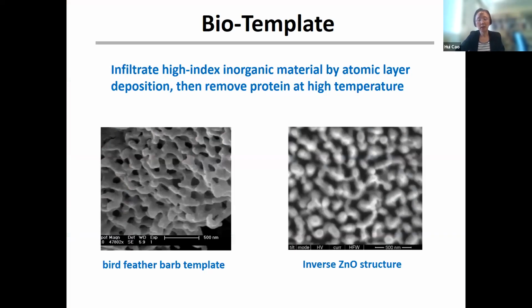But typically this phase separation worked very well, usually for soft matter, like a polymer or protein. But those soft matter usually have a relatively low refractive index, meaning they are not going to strongly scatter light or reflect light. To really enhance the color, we like to increase the refractive index contrast. And usually the inorganic material, like a semiconductor or some oxide, can have higher refractive index. But we don't even know how to make this kind of structure using soft matter. To make it with hard matter is even more difficult.